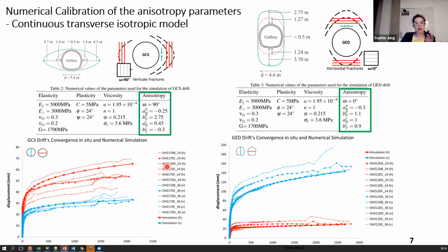And the anisotropy of convergence in the model is assumed to be due to the fracture. So we assume that the direction of anisotropy is the same as the direction of the main fracture around the drift. So basically for GCS drift, you have a vertical fracture, and hence transverse isotropy oriented in the vertical direction, and the anisotropy is rotated by 90 degrees for GED drift, as the fractures are oriented more in the horizontal direction. The parameters of the plastic and viscous anisotropy are defined by numerical calibration by comparison to the in situ observation.